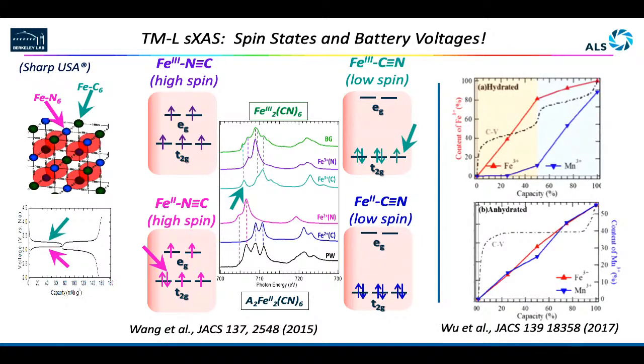To make it more practical in the industry, it has been a puzzle that a trace amount of water in your material will change your battery voltage completely. So this is another example. If you have water in your electrode, it will behave like this. This curve is the electrochemical performance, voltage versus, again, the current, meaning the capacity. But if you dry out your material, it becomes a much preferred curve. The industry really loves this kind of charge and discharge curve instead of two plateaus.